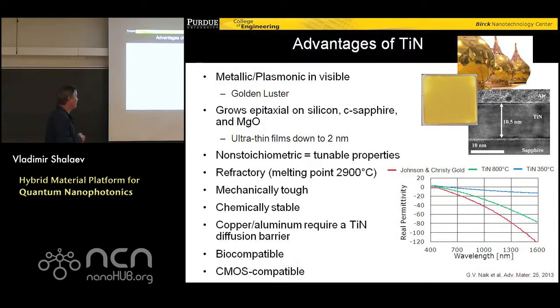It's chemically stable, it's biocompatible. This material is used, for example, in implants, in dentistry, which is very important; it could be used for biomedical applications. It's refractory, it can sustain very high temperatures. This is very critical because with plasmonics, we focus light down to the nanoscale, meaning that we have very high energy densities. It unavoidably results in an increase in temperature.